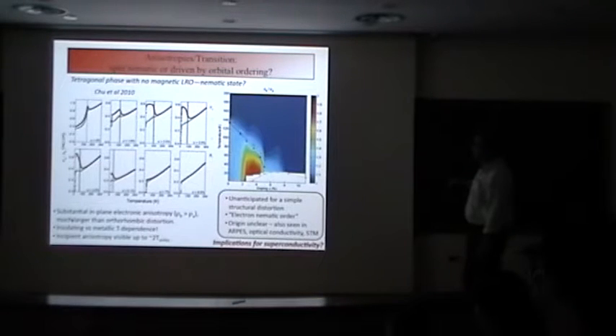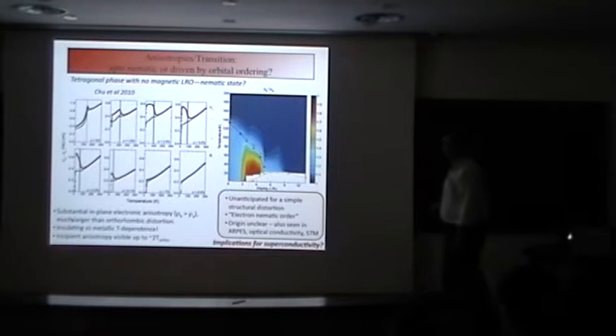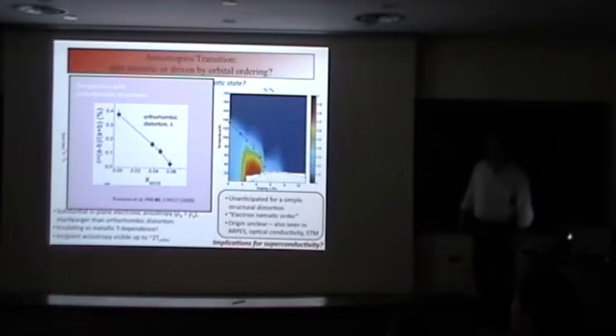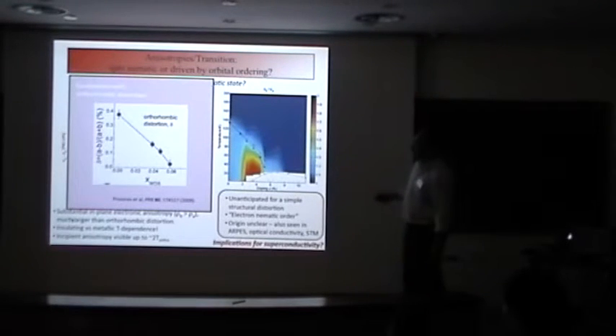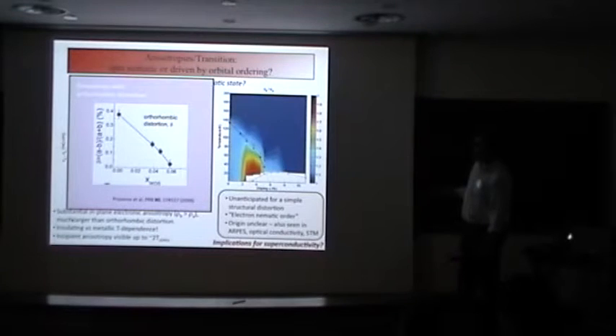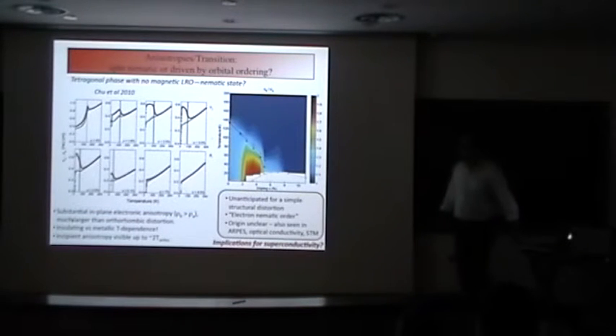This is a color plot showing the resistivity anisotropy going up to a factor of 2 as you get closer to the point where superconductivity is coming up and magnetism is going away. If you look at the magnitude of the structural distortion, it's less than 1% or so and comes down with doping, whereas the transport anisotropy is a factor of 2 and goes up as one increases doping.